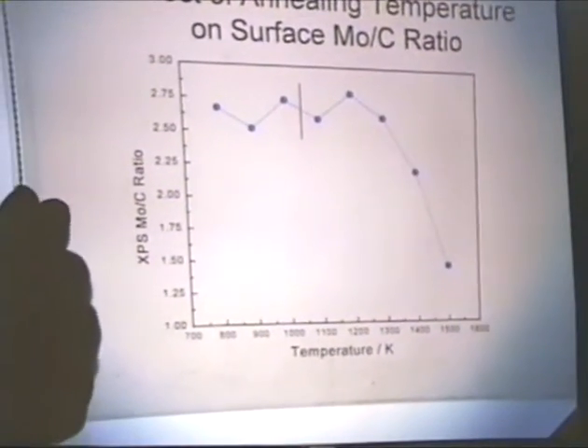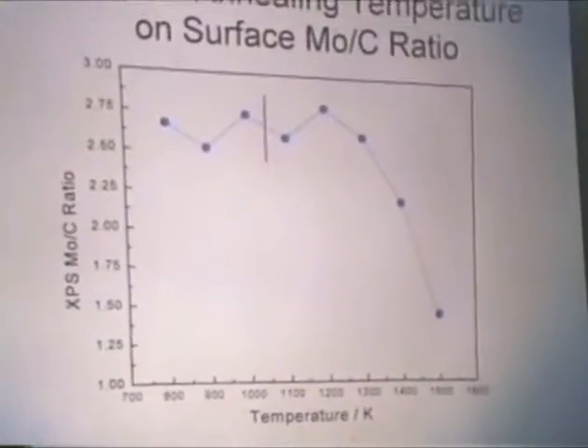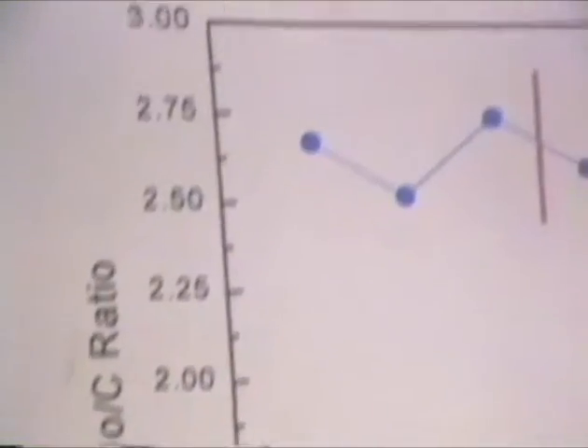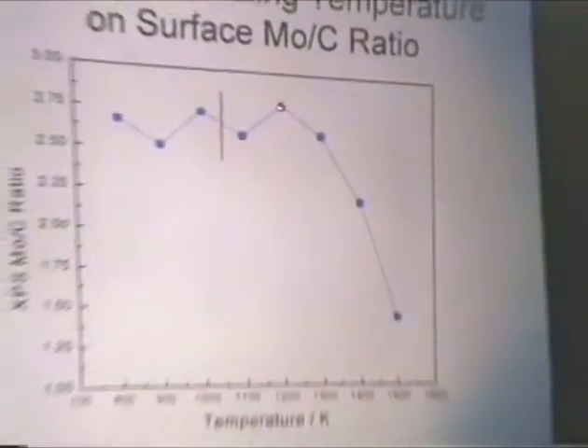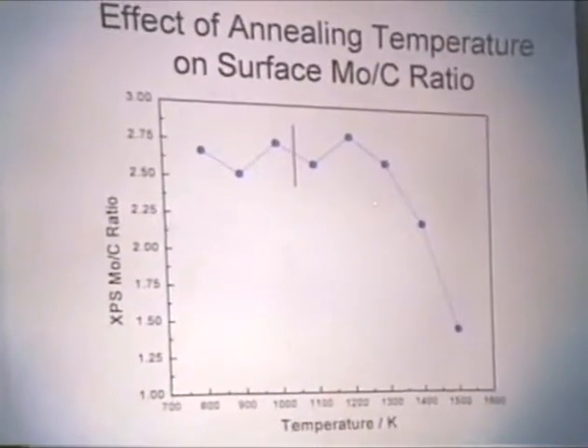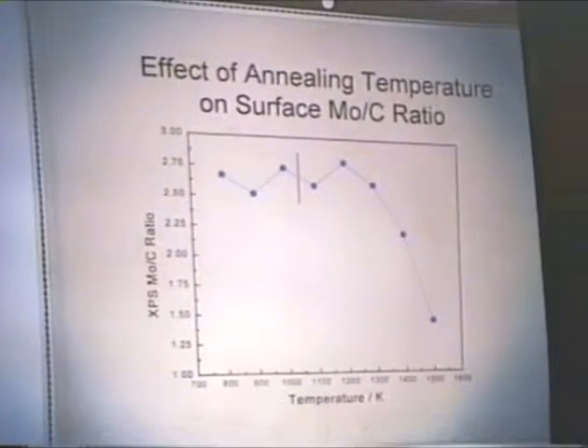We've studied the effect of the annealing temperature on the surface moly to carbon ratio as calculated from XPS data. And you see that between temperatures of 800 and 1300 Kelvin, we get a relatively consistent value of surface moly to carbon ratio, between 2.5 and about 2.8. However, above 1300 Kelvin, you see this drops off drastically.